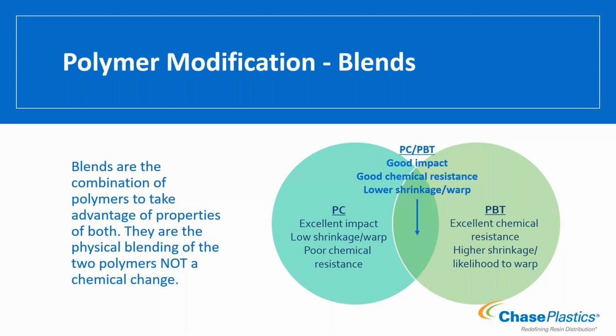So overall, if we combine the two, we end up with a material that has good impact - not as good as PC, but better than PBT. It's got good chemical resistance - again, better than PC, not as good as PBT - and it's going to have lower shrinkage and lower likelihood of warping than your PBT would, but not as good as PC. So when we blend these materials together, we end up getting a nice combination of performances.